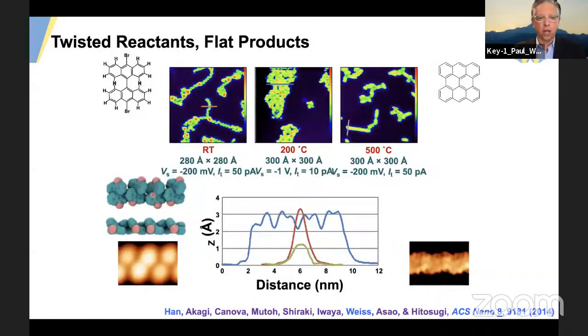He started showing that we could form these complexes of the reactants. He could raise the temperature to break the carbon-bromine bond and measure the intermediates by lowering the temperature again. And then at higher temperature, he could form the chiral graphene nanoribbon, very much like the arrow pushing that we teach in organic chemistry classes.